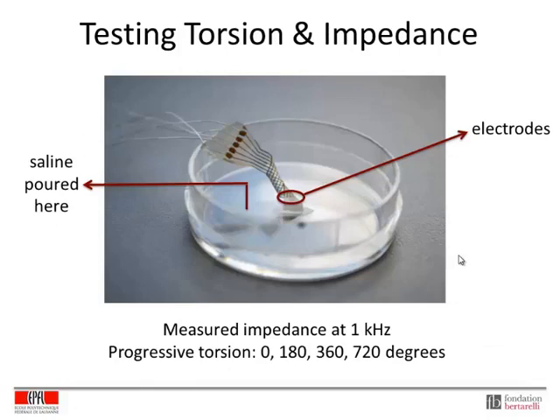In order to fully characterize the mechanical robustness of our electrodes, we also must test the impedance during torsion. First we check the general behavior of the impedance during single progressive torsion. We go from 0 to 720 degrees at 180 degree intervals. We fix this device, glue it down to a petri dish, and fill everything with saline to ensure that the electrodes are fully covered, and then clamp the top as we do our progressive torsion. Then we measure the impedance at 1 kilohertz frequency.